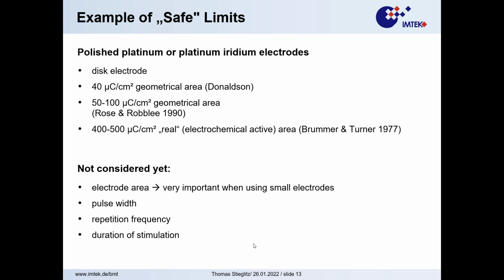is the safety limit. If you go on, Timothy Rose and Robblee have passed away, so you cannot ask them any longer. They have reported in their publications it's between 50 and 100 microcoulombs per square centimeter geometrical area, which is close to 40, so we're still in the same order of magnitude. But you find others, Brummer and Turner, and they said we take 400 to 500 microcoulombs per square centimeter. That's a factor of 10.